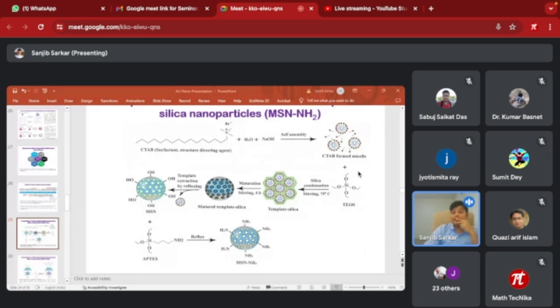You see, this dextran is bound to the phenylboronic acids by a covalent bond here. So the phenylboronic acid and dextran bind each other, and the pores are closed, and the drug gets entrapped into the nanoparticle. After this, we did some characterization of the nanoparticle, and we found that our nanoparticle